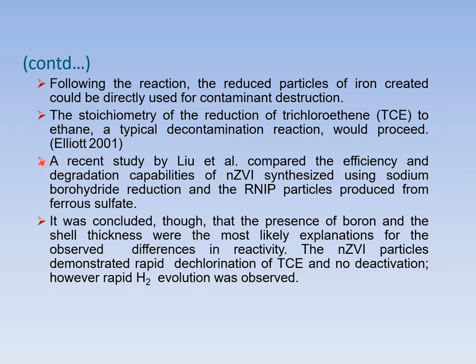A recent study by Liu et al. compared the efficiency and degradation capabilities of NZVI synthesized using sodium borohydride reduction and the RNIP particles produced from ferrous sulfate. It was concluded, though, that the presence of boron and the shell thickness were the most likely explanations for the observed differences in reactivity. The NZVI particles demonstrated rapid dechlorination of TCE and no deactivation. However, rapid H2 evolution was observed.